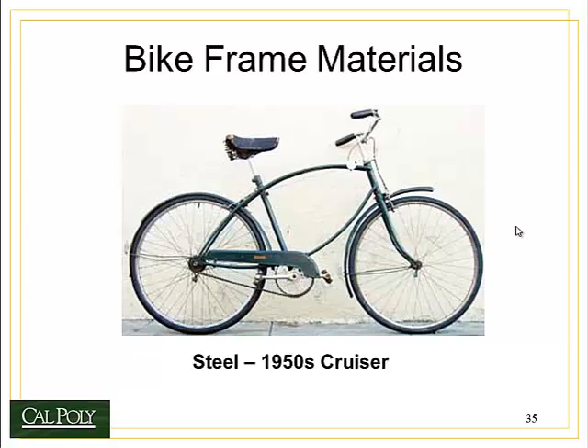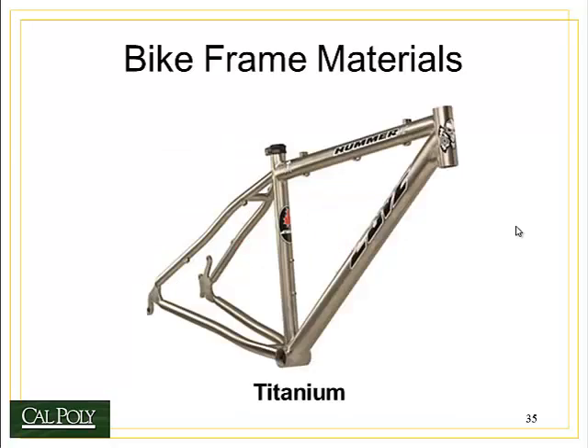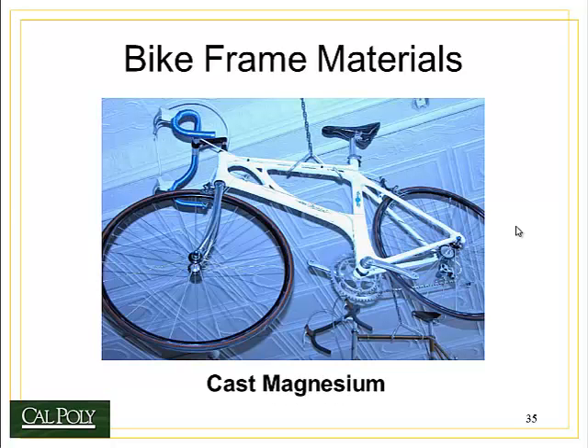In the 1950s, bicycles were largely made out of steel — it's very cheap, very easy to form into the proper shape, but also very heavy. Aluminum is today a much more common material; it can be cast or welded into the necessary shape and it's very lightweight, though a little more expensive. If we need an even lighter, high-performance bicycle, we might go with a titanium frame. Titanium is so much stronger than aluminum that we can use less material, and it has a fairly low density, so the bike frame overall is much lighter. But titanium is ridiculously expensive, so such frames are usually out of reach of the average bicyclist.